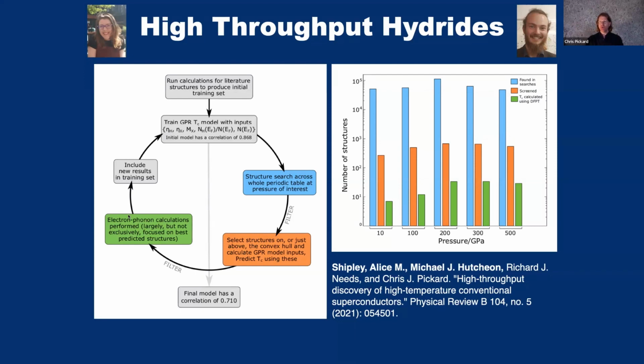So what we did were a bunch of high throughput calculations. Doing random structure searching is itself a high throughput calculation, where we take multiple initial configurations of a particular composition and relax them and see what the most stable structure is. But then we took this up another level by having multiple compositions being done at the same time as well, and feeding these onto very large computers with very large numbers of cores.